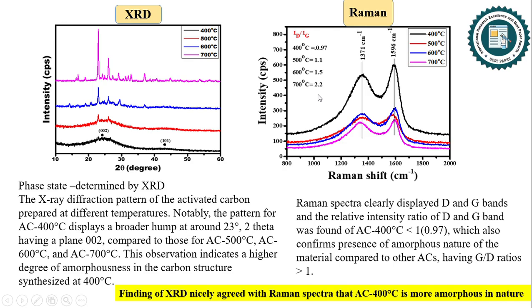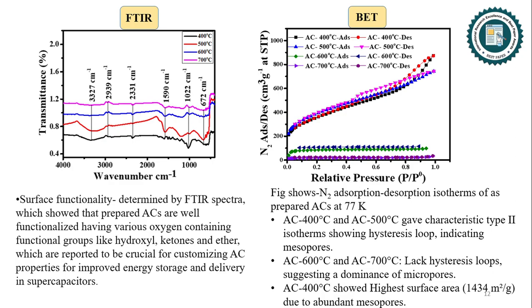So the findings of XRD nicely agreed with the Raman spectra that activated carbon AC 400 degrees centigrade is more amorphous in nature. The surface functionality of the activated carbons was determined by FTIR spectra, which showed that the prepared activated carbons are well functionalized, having various oxygen-containing functional groups like hydroxyl, ketones, and ether, which are reported to be crucial for customizing activated carbon properties for improved energy storage and delivery in supercapacitors.